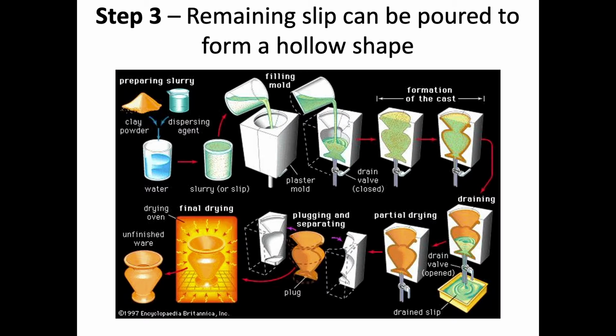Okay, so in step 3, this is if we want to make a hollow shape. So we've allowed the liquid to wick into the mold wall, so you can see it happening here. And so that tan color represents the powder that is compacted on the side. So if we want a hollow shape, what we can do is drain the rest of the liquid, and we leave behind a thin wall material, like is shown here. And so we still have some slip left over, but that's okay. So we can remove the remaining slip if we want to form a hollow shape.